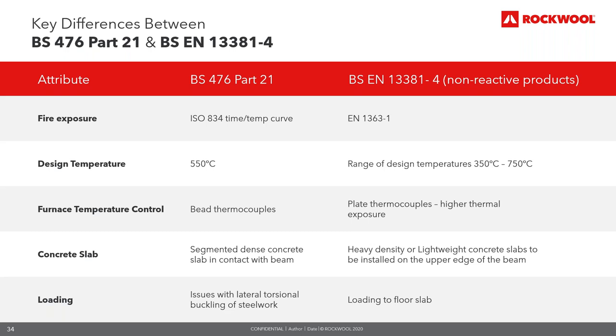Temperature control within the furnace has also changed. BS476 utilizes small bead thermocouples, which respond very quickly to changes, especially in the early stages of a test, and they only require small increases in fuel input per unit change in temperature. Under the European standards, plate thermocouples have been introduced, intended to reduce the differences between fire tests carried out in different furnaces and thus to promote European harmonisation.